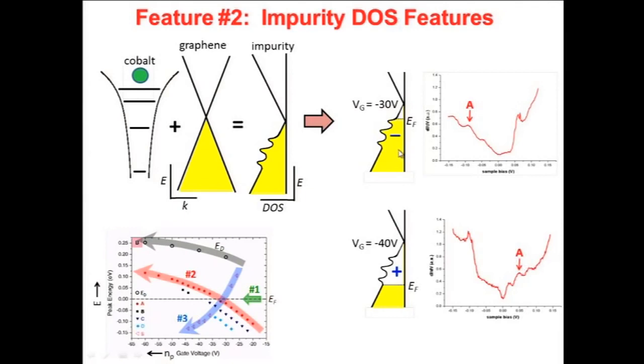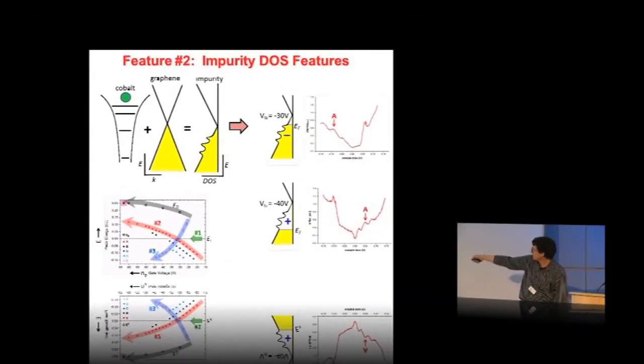And here you can see the actual data. This is the dI/dV versus voltage, and these are the impurity states below the Fermi energy. Now here, I'm showing you the same atom, but with a different gate voltage. So now those states have been pushed above the Fermi energy. And I put a little plus sign there because now the charge has flowed out of those states. So now we've depleted, we've removed charge from that cobalt defect. And here you can see that in the data. Here are those same states, but now pushed above the Fermi energy.